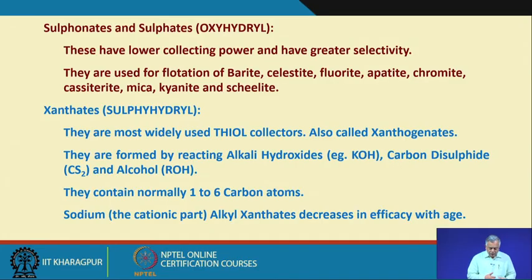They normally contain 1 to 6 carbon atoms. Sodium is the cationic part, and the alkyl xanthates decrease in efficacy with age. That means if it is freshly produced, it will have much more efficiency than if it was produced earlier.